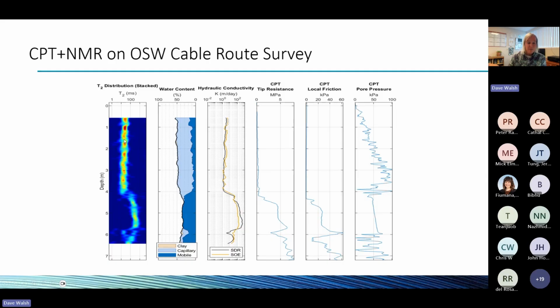Well, definitely you've got soft sediments here, although those relaxation times are not that long. These are silt-like relaxation times, not clay-like. And then there is a pretty well-sorted sand deposit here. It trends from a little bit finer sand to a little bit coarser as you go through it. It also gets particularly well sorted right here. And then below that, you have an interesting mix of pore sizes, indicating different sediment grain sizes mixed together, or perhaps very thinly interbedded. You also have estimates of hydraulic conductivity, which range up to 100 meters per day, a couple hundred meters per day down here. That's pretty high.